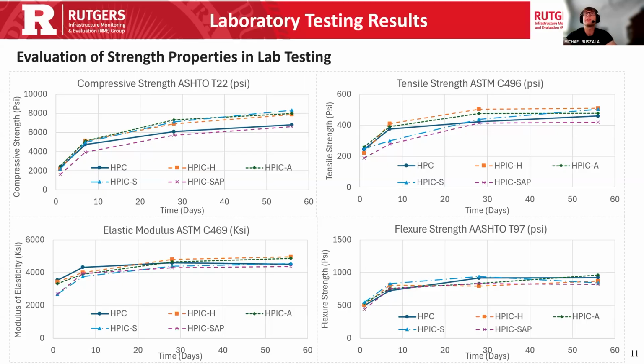That's expected because once again, these effectively water beads leave a void once the water disperses. So it's a little bit of, I guess you could say, a defect is left and the strength is slightly reduced, but you do see a lot of benefit with the shrinkage. So you need to weigh these options.